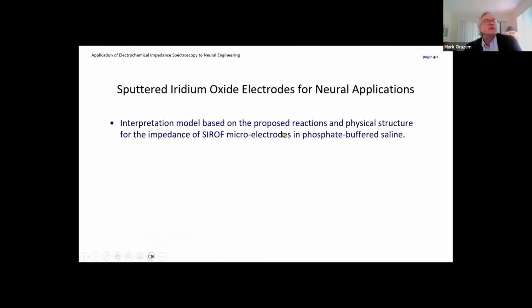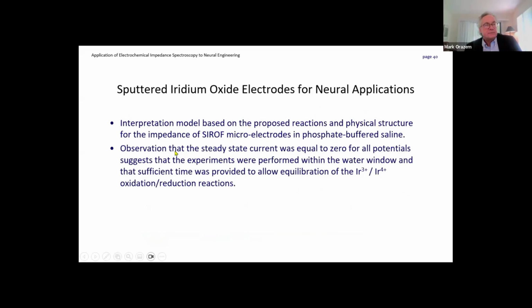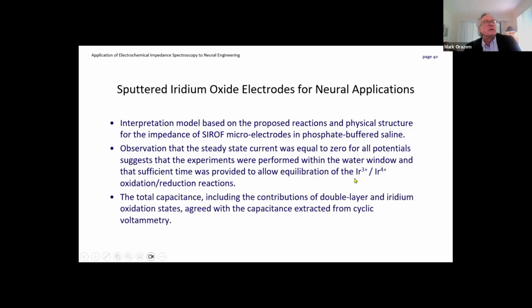So what we're saying is that our interpretation model is based on proposed reactions and the physical structure. Our observation that the steady state current was equal to 0 suggests that we were well within the water window and that sufficient time was provided to allow equilibration of the iridium oxidation and reduction. And the total capacitance that we obtained, which includes the contributions of the double layer and the iridium oxidation states, agreed with the capacitance extracted from cyclic voltammetry.